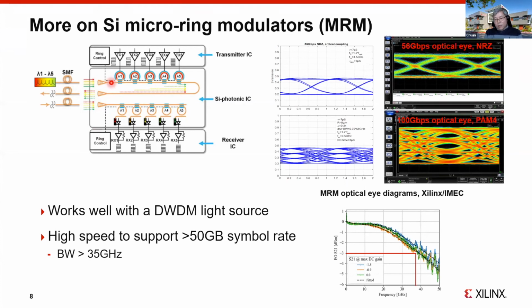The optical modulation amplitude, or OMA, is basically the power difference between your 1 level and 0 level. So the OMA is 6 dB below your incoming DC power. Say you have 1 milliwatt of optical power coming into a ring modulator, you can get a quarter milliwatt of modulation amplitude coming out.